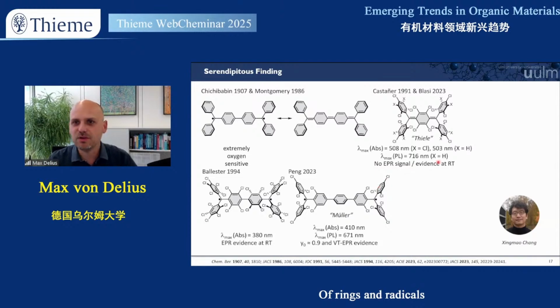Xingmao then showed me a literature overview, and I actually in the beginning couldn't quite believe it because I really thought this kind of molecule must be known in the year 2024. But it turned out in this whole zoo of other diradicals, some of them were revisited in 2023, the molecule was missing. And we knew from the beginning, from the blue color, it is very, very different from the compounds in the literature. So it obviously redshifted even compared to the Müller diradical, which has a longer conjugation chain, and compared to the Thiele diradical, which is not even a diradical really, because it's just quinoidal.